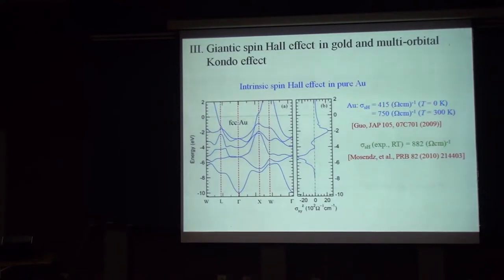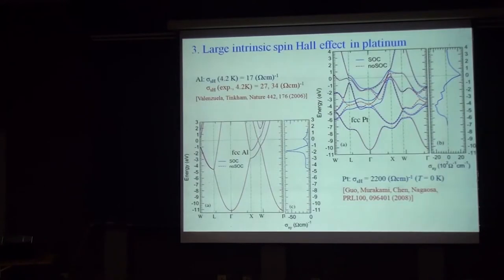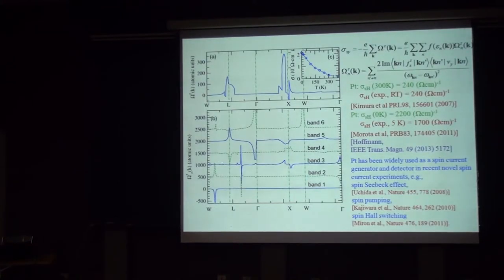If we look at band structure here, there's a crossing here. By the way, this is two sets of band structure. The red one is without spin-orbit coupling. The blue one is with spin-orbit coupling. And the gap is very big. Because the platinum is very heavy, atomic number of 78. So, spin-orbit coupling is huge. So, the gap will be about 1 eV. Now, whenever this accidental crossing degeneracy is lifted, you will see two peaks. One is going this way, and the other is going that way.